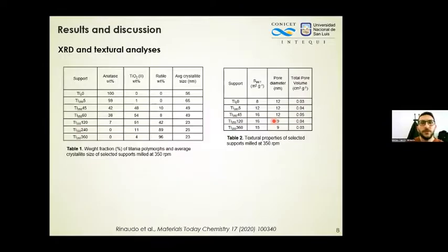Then we went through some calculations of a rough estimation of the composition of each of these three polymorphs, taking the equations from the literature and the most intense reflections of each of the crystalline phases. And we also estimated the average crystalline size, and we obtained some values in accordance with the milling time.